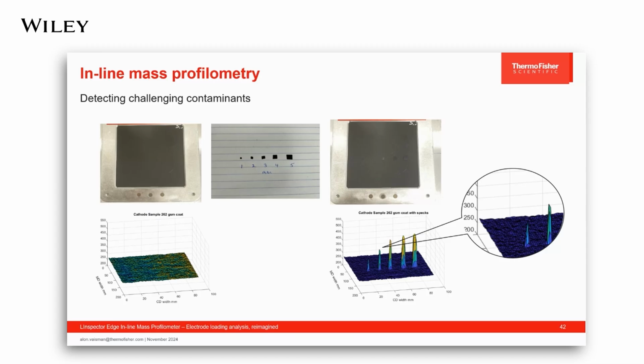Looking at the photo of the electrode on top, you can see the larger flakes with some effort. The smaller flakes are much harder to see. There is no color contrast, and the optical inspection system would struggle to detect this type of defect. The mass profilometry data, however, makes the flakes easily detectable. The difference in mass in the local area where the flake is placed is very large and is easily picked up by the system.